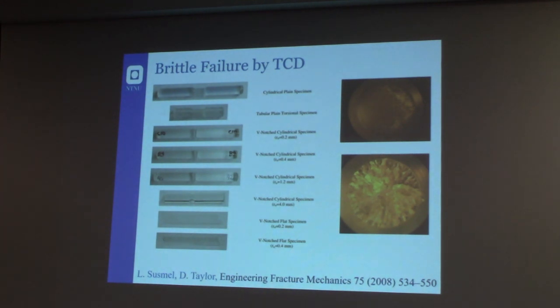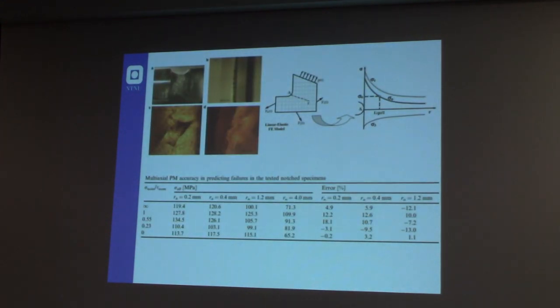And I think one of the most relevant papers, if you are interested in this topic, is this one published in 2008, where they were able to apply this kind of theory of critical distance to brittle failures of polymethyl methacrylate, considering mode 1 and mode 3, and also mixed mode 1 and 3 in combination. That was quite new at that time in 2008, and they obtained very good results in terms of predictions, with some peaks in the errors, but not a big mistake.